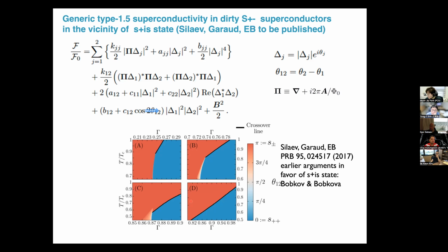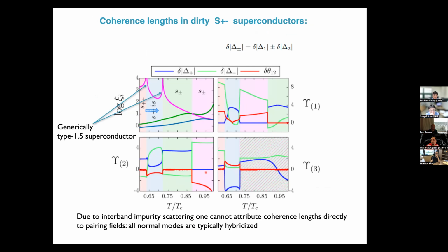But if you do a very small modification of the model, if you have broken time reversal symmetry, then strictly speaking, there is no Leggett mode in the usual sense, because you start mixing densities and phase difference. So your Leggett mode becomes mixed with amplitude modes. And that you can measure. Since it is mixed with density modes, the inverse mass of this mode will determine the vortex core size.